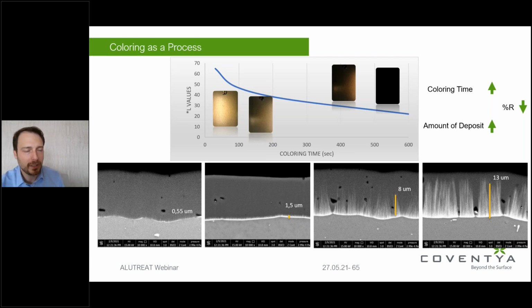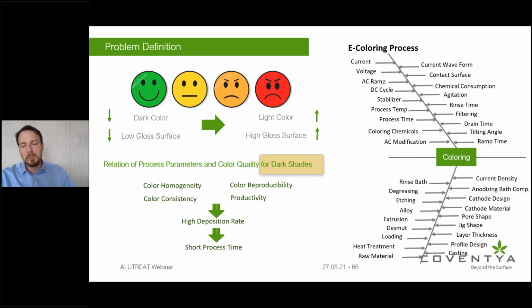So not only the problems that are occurring with light shades are originating from the base metal or the oxide layer structure, but they are also strongly related to how much precipitate or how much metal salt you're having in your pores and how well they're distributed. Therefore, it is paramount for the reproducibility of the electrocoloring to separate what we're going to do. For dark shades, we are expecting something else from the system. That means process time. You don't want to be too long in this process, the precipitation efficiency, and then adjusting the parameters.